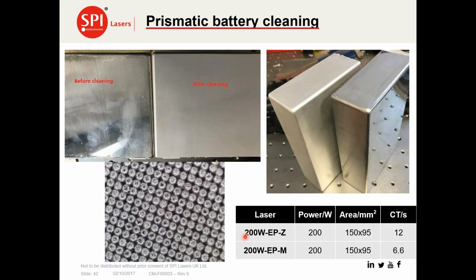And again, here we're showing the difference between 2 lasers of similar laser power, but with different beam quality. The EPZ has a beam quality of better than M squared of 1.6, whereas the EPM is somewhere around 5. And because it's a larger spot size, more top hat in terms of the energy distribution, it is more effective at processing large areas.